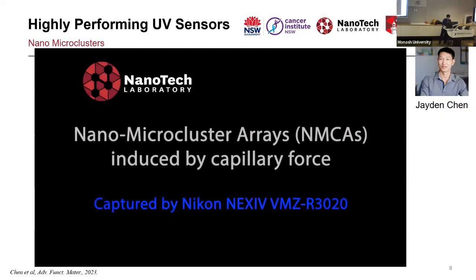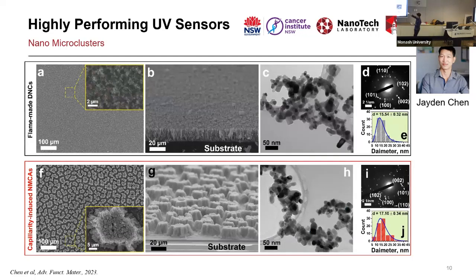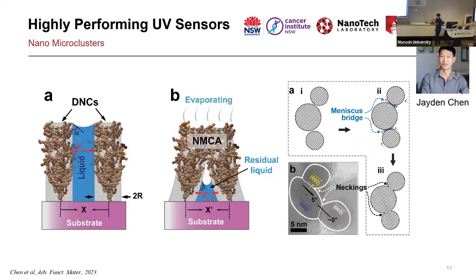So why is this interesting? The top row is a flame-made one. You put your substrate there, spray by flame, top view, high magnification, 8-degree tilted, and that is your structure. You put a 5 microliter droplet, one minute later it is dried out, and that structure is changed into this one. All these volcanoes maybe, or to me sometimes, if I don't have a good day, a dead forest, like you killed all the trees. It depends how I started my day, but that structure is changed into this structure, and you see the electrodes at the bottom. This structure is now patented by Macquarie and is licensed by 2 companies because it gives us significantly higher performance in sensing applications.